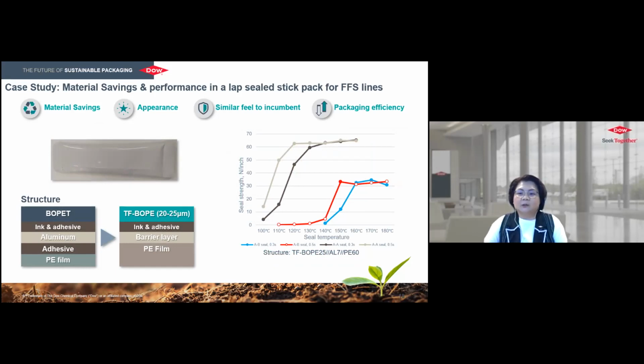One of the key performances to evaluate for lap seal stick pack is also the seal strength of the sealant to sealant, which in the graph is expressed as the light and dark gray curve, as well as the seal strength of the sealant to the other surface of the print replacement substrate, which is expressed as the red and blue curve, under different sealing time with the same sealing pressure applied. From the evaluation, it is expected that sealant to sealant seal strength will be good, and with Dow's unique solution in polyethylene resins used in the sealant layer, we can achieve a good heat seal initiation temperature. Even when we are sealing the sealant layer to the TF BOPE film, which is the red and blue curve, we can again see that decent seal strength of up to 30 Newton per inch can be achieved.